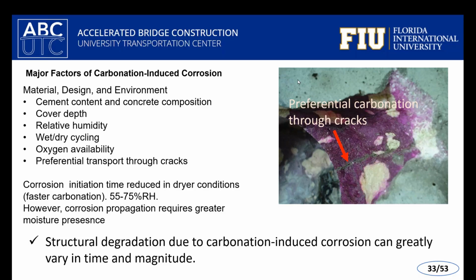But you also notice that we had this hairline crack. Well, it's maybe a little thicker than hairline, but this fairly thin crack that occurred on the concrete surface. And you notice that the phenolphthalein didn't color that purple. So we have this thin interface that's carbonated. Essentially CO2 is able to penetrate even through this high performance concrete and carbonate a thin layer. In this particular system, the crack penetrated fairly deeply, all the way to the interface with the steel rebar.